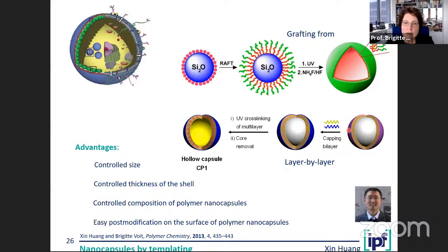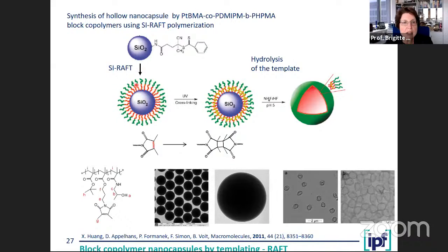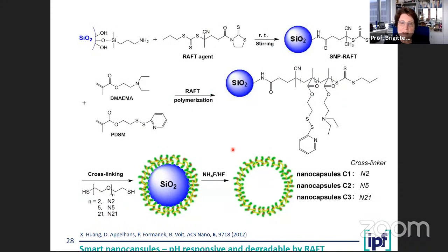The other approach we also used is, again, starting from a template, and on the template, you actually build up layer by layer a shell, and this shell you also cross-link. So that is the layer by layer approach, and finally, after cross-linking, you can also remove the core and have the capsule open. So both were used. You see here some pictures. We used again controlled radical polymerization, the so-called RAFT process. Did the cross-linking, removed the core, and you see beautiful capsules which resemble now in size the template which we used. And you can even make some more nice chemistry.